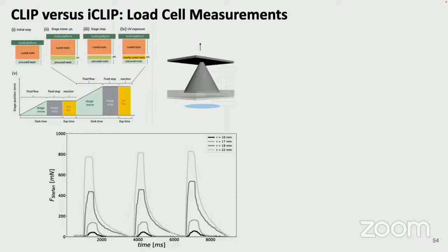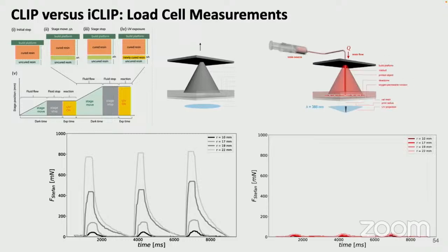And depending on the width of the part, that adhesion force is higher. So here's where the diameter is very high. You pull the platform up. We put a load cell on the platform, measure the loads, the forces. You pull the platform up, you stop, and you wait for the liquid to fill into the gap. And there's a stress relaxation that takes place. Depending on the diameter of the part, as the diameter goes down, the forces are lower. But look what happens with injection CLIP. Those forces can go away. In fact, you can get a negative force. This is like walking up to a wall with a fire hose. You're getting pushed back the other way. And so the forces go away.